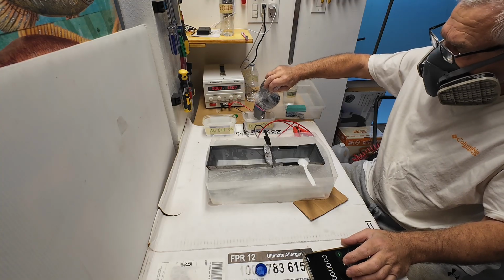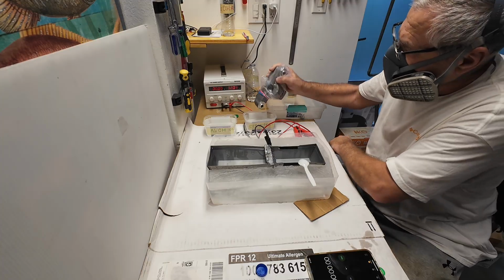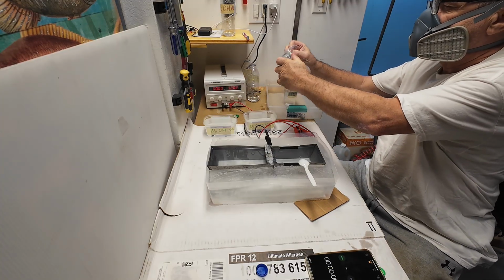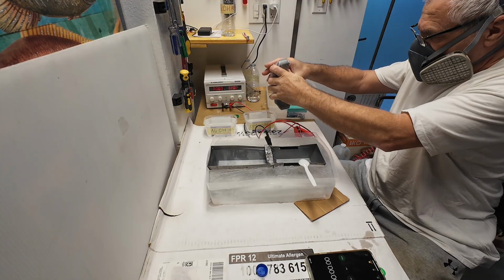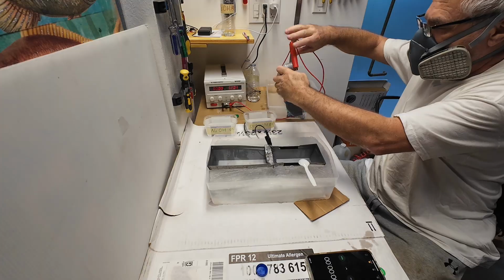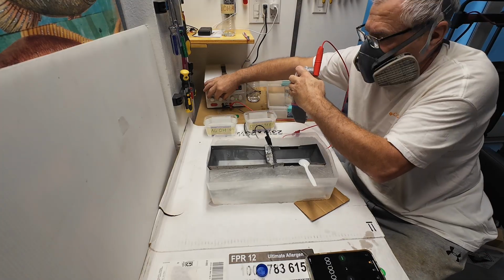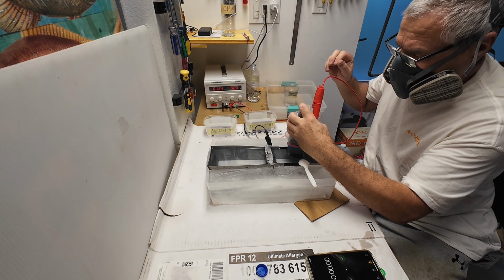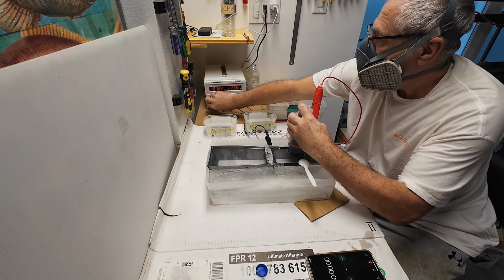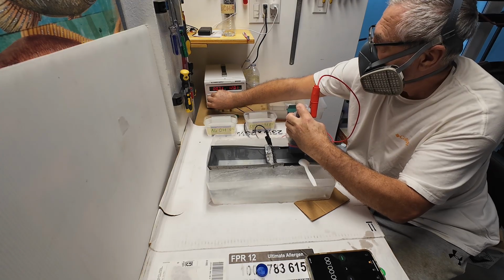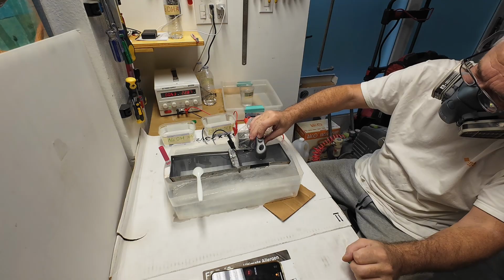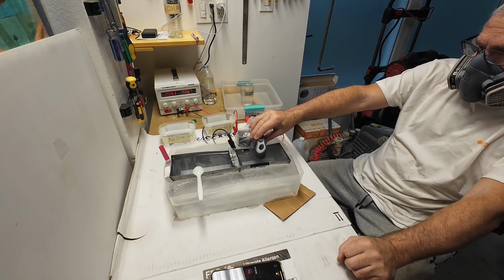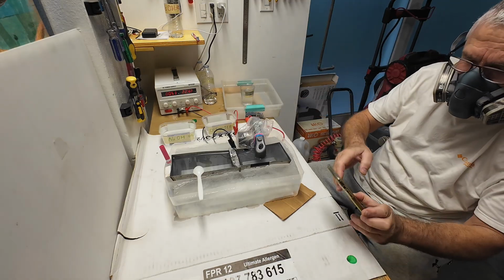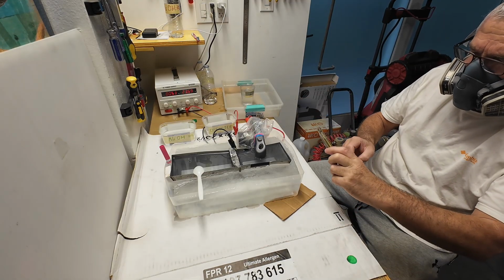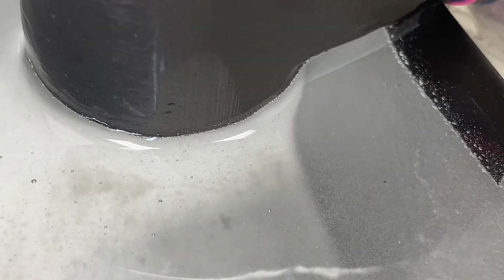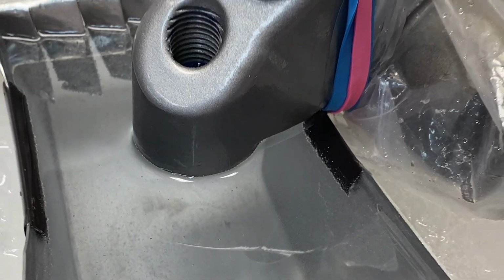First the alkali, then distilled water, and finally I immerse it in the electrolyte bath. I sealed the internal steel threads with the sealant, apparently without success, as the anodizing process failed to initiate. I had to reposition the shaft, so that the electrolyte wouldn't come into contact with the internal steel threads. With this arrangement, the reaction proceeded normally.